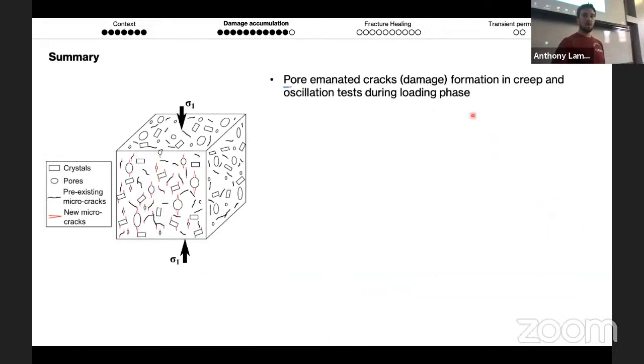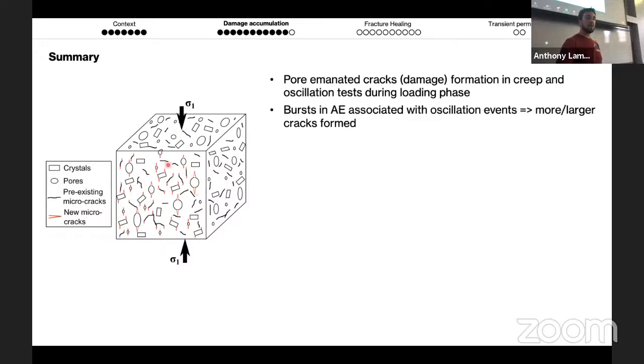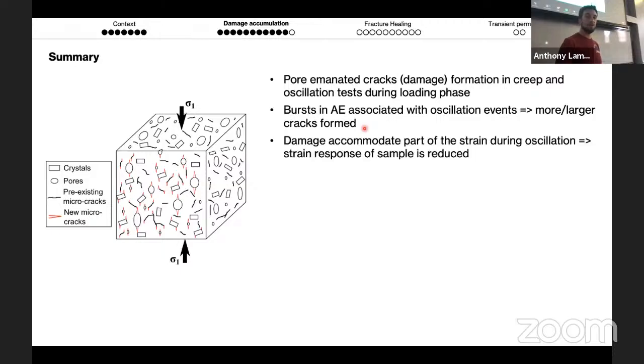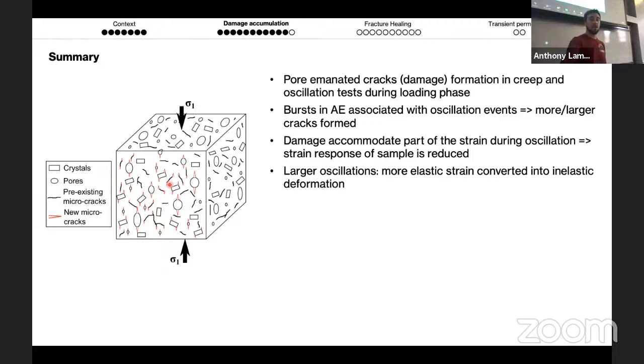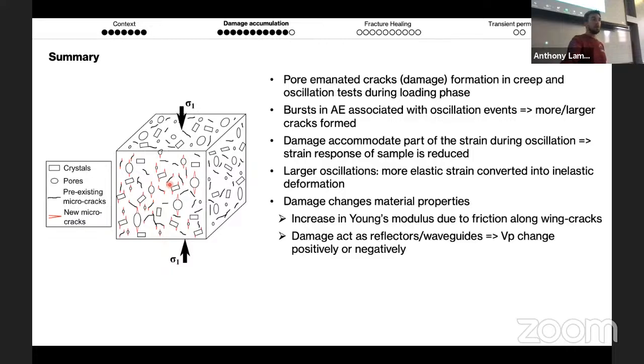So I'll summarize pretty much all of this. During my tests, the sigma 1 applied will generate these pore-emanated cracks. As you put in the oscillation, you'll create more of these cracks and then generate bursts in AE, or the cracks will be larger. The damage that is accumulated during the strain, the strain that is taken by forming these cracks, will at the next oscillation event give an apparent reduction in straining. What I've shown in the last few slides is that the larger oscillations convert more elastic strain into inelastic deformation. These result in changes in mechanical properties.